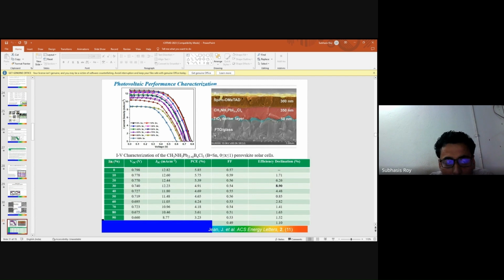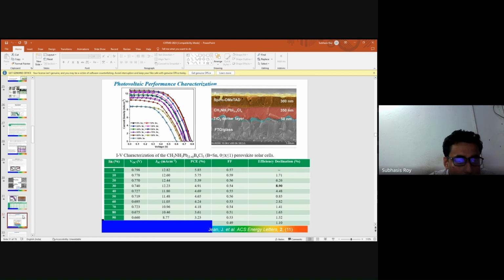So these are the structural output results finally in our Sn-based solar cells, where we can see that around 20 or 30% Sn is giving the maximum efficiency and fill factor. And this is the cross-sectional view of the fabricated solar cell thin films, and this is the IV characterization and performance analysis of the solar cells. This paper is published in the ACS Energy Letters journal. And from here, we can conclude that the optimized percentage of Sn, around 20 to 30%, is giving the maximum efficiency of the solar cells.